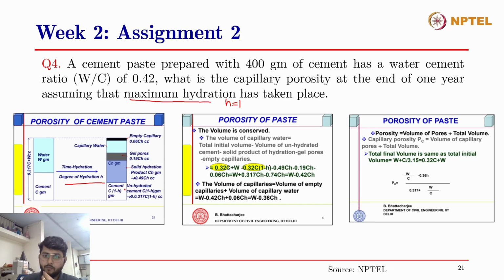Gel pores will be around 0.19 cm³. We have already calculated this in the lecture itself. Then we'll have capillary pores, and then empty capillary of 0.06 cm³. And if we conserve the volume before hydration and after hydration, then we can find the volume of capillary water.